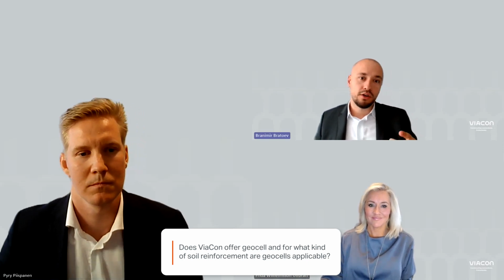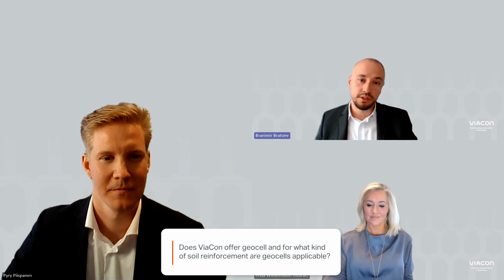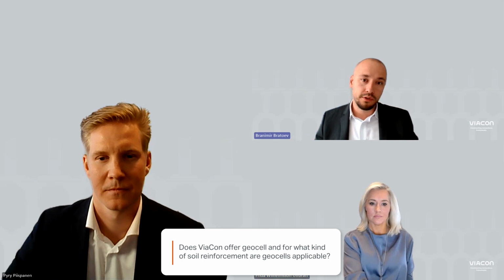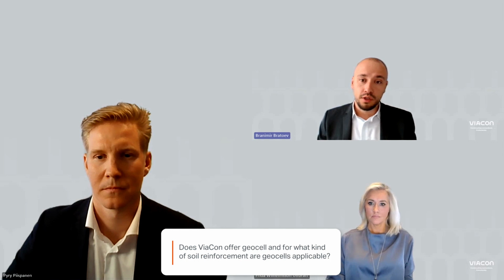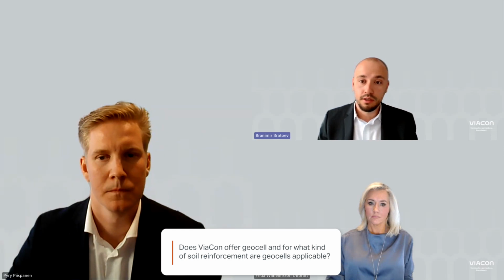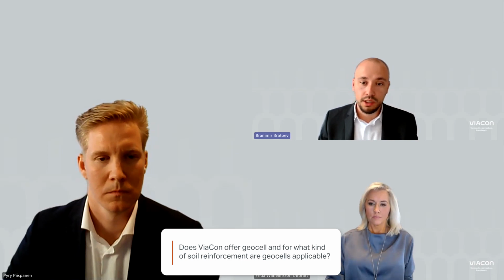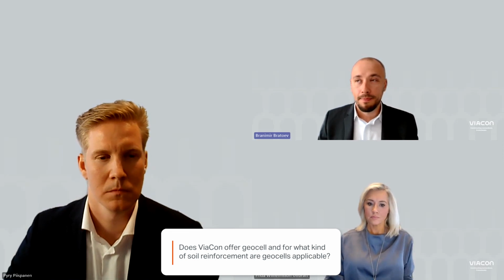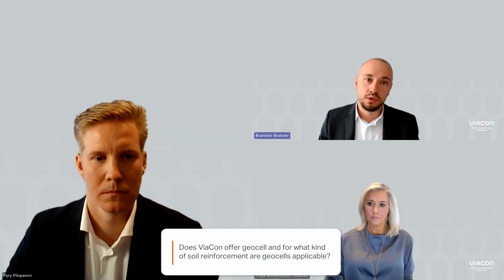Let's explain what geocells are. They are honeycomb-like geosynthetic material made of polymer, and usually the height is between 5 and 30 centimeters, and the opening is different depending on the application. And yes, we can offer that kind of solution, but very often this is not our first choice, as we recommend it for base course stabilization only when we have limited opportunity to go deep due to geological obstacles, communication, or gas pipelines. Geocells have also very wide applicability in erosion control of steep slopes, water channels, and many other applications. Very often these geocells are combined with non-woven geotextiles below them because we need a separator.